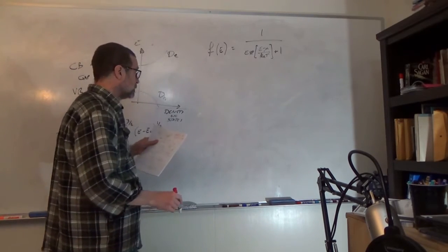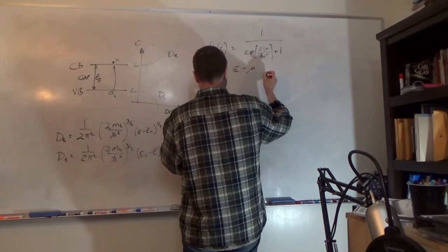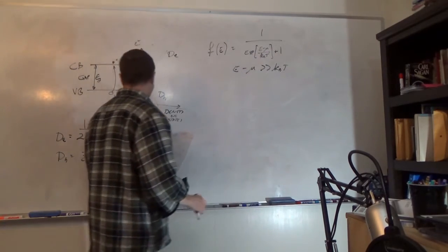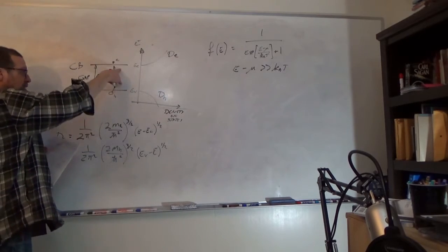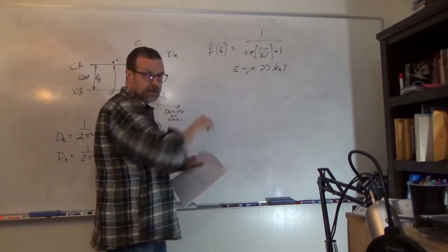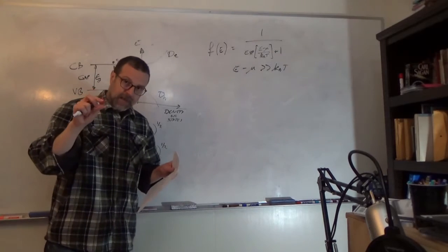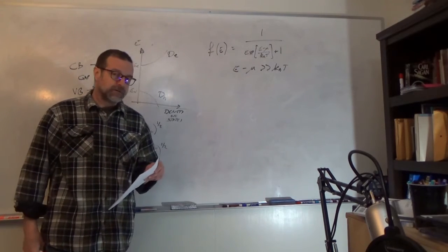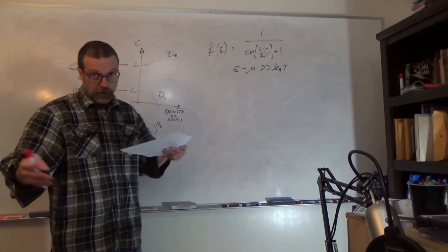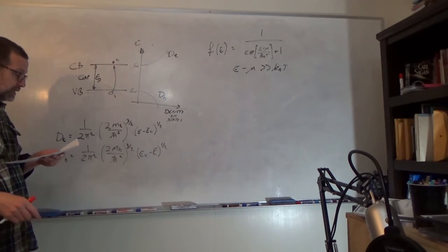Now we want to talk about the distribution of electrons within the density of states, so we go back to Fermi-Dirac statistics: f(E) = 1/(exp((E−μ)/k_BT) + 1). Note I put the chemical potential in rather than the Fermi level. When E − μ is much larger than k_BT — and such is the case in most semiconductors, since a band gap on the order of 1 eV is much larger than 25 meV — we can take an approximation.